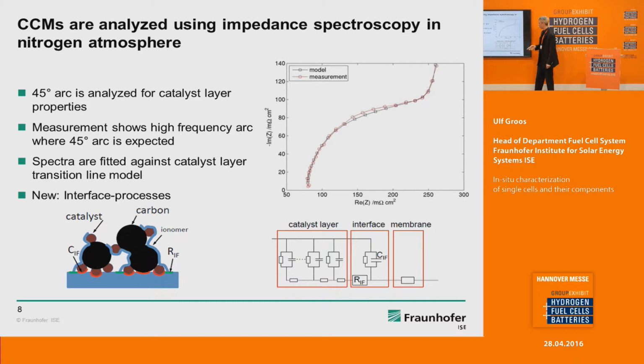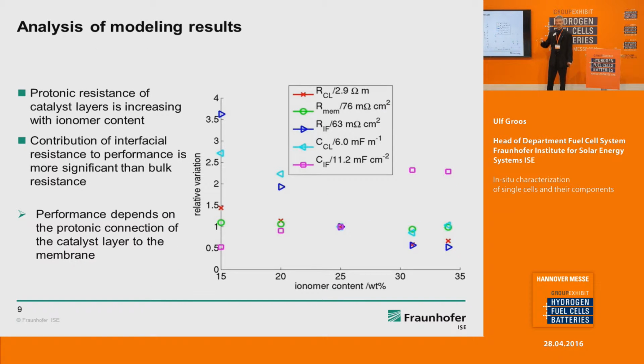So we created an electrical circuit model, and we specially introduced effects that might occur from the interfaces. So we introduced interface resistance from a membrane to an ionomer, and an interface capacity from membrane to the catalyst particle. And by doing so, we could then analyze the dependence of the different parameters, which are shown here, on the ionomer content. And by that we realized again that the ionomer content has a great influence on these parameters, and especially these interface parameters are crucial. So by that you can learn how a certain ionomer content or a composition of your electrode affects the performance, and on the long term the degradation.